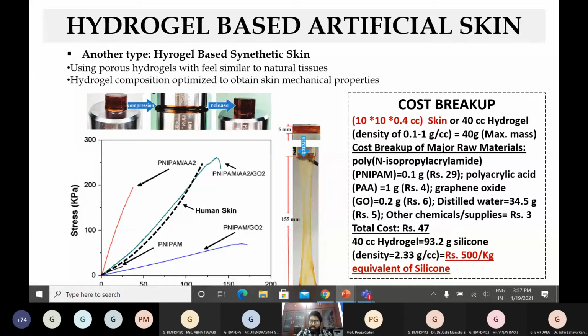We compared the cost. It comes out to be around 500 rupees per kg equivalent of silicone. So 1 kg of silicon would usually cost us around, let's say, 250, 300 ish. So this came out to be around 500, which is around 70 to 80% above that. Not that bad. We thought it would be 4 to 5 times. So this is how we do the cost benefit analysis of this as well.